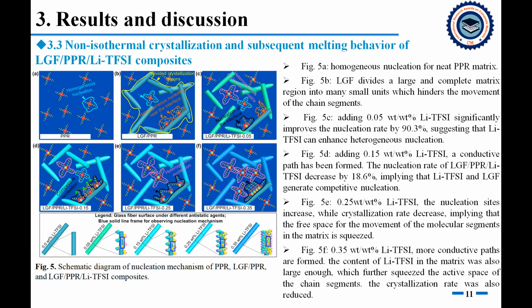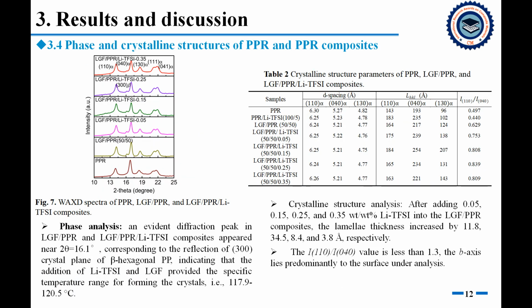Then the organic salt content is 0.35 weight%. More conductive paths are formed. The content of the organic salt in the matrix was also large enough, which further squeezed the active space of the chain segments. The crystallization rate was also reduced. We further studied the microstructure of the composite material, such as the type of phase, the thickness of the lamellar crystal, and the growth direction of the lamellae, and obtained the evolution law, which laid the foundation for establishing the relationship with the mechanical properties.